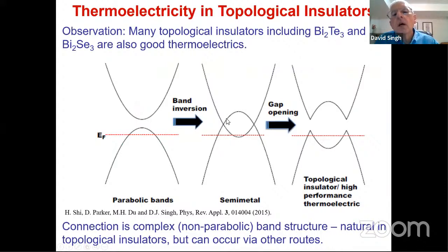And then there's some other interaction that stops these bands from crossing. That can be spin orbit, as it usually is. And so a gap opens. And so now we have our topological insulator, and depending where these crossings are, the topology can be different. But the basic story is this has the character of the old conduction band. But then the character for the old conduction band occurs here. And this has the character for the old valence band from here. And so there's a change of character, and there can be a topological aspect to that here.